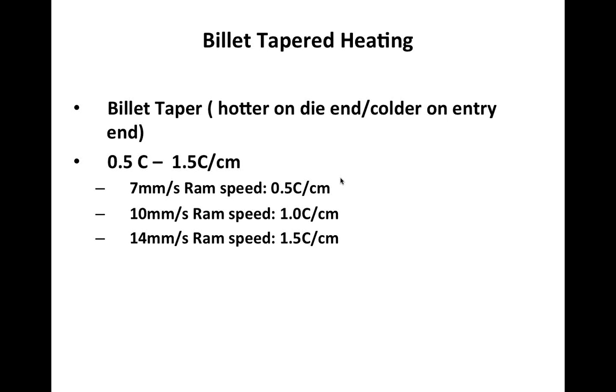Most of the new presses offered today offer a maximum of 100 degrees Fahrenheit taper in a billet, or 50 degrees Celsius. The reality is, to attain isothermal extrusion today, we're looking at tapers anywhere from 100 up to 300 degrees Fahrenheit. And I would say 300 degrees is extreme, but there are extruders today using up to a 300 degree taper on the billet. The goal by having a taper in the billet is to have minimal, if any, variation in ram speed, to have a relatively consistent ram speed and a consistent exit temperature.